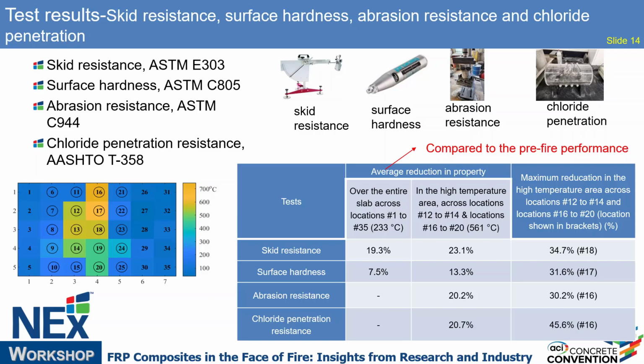And what we found is that on average, if we consider the whole slab, the temperature increase is 233 degrees C. The skid resistance was reduced by 19.3%, and the surface hardness was reduced by 7.5%.